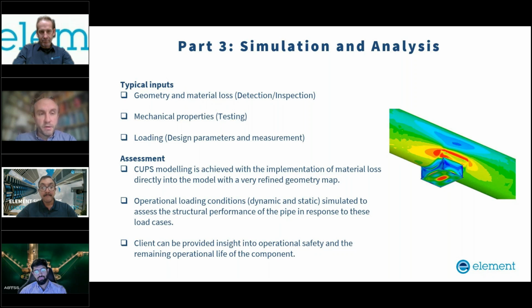In terms of the testing that was done, that Basab has referenced, we can bring that forward and convert that into suitable mechanical properties, tensile properties that can give us some feel for how the material might behave in an elastic plastic nature under a given series of load cases. And those load cases will be a function of the internal pressures, the local stresses that are being seen as a result of the response to the attached components, the supports, attached pipework, and so on.